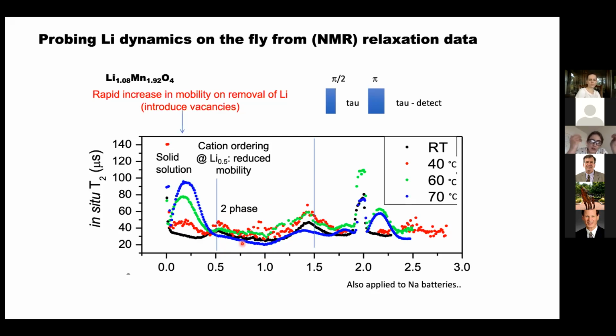In the same way that you can think about variables in a phase rule, you can then determine that if this parameter is a continual variant, then that sets the number of phases in the system, and it becomes a solid solution. While it's a constant, it's a two-phase reaction. And then what's interesting is where we saw this cation ordering at low temperatures, you can see that when you heat up to higher temperatures, you no longer get this cation ordering. So just by doing these experiments, without knowing all the details of the interactions that drive these things, you can say something about the phase transformations that occur in these materials.